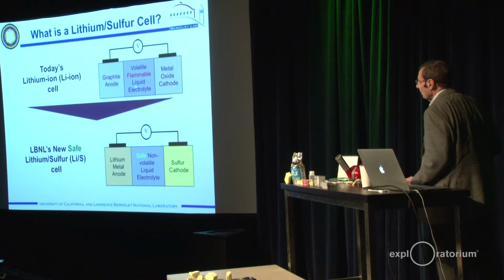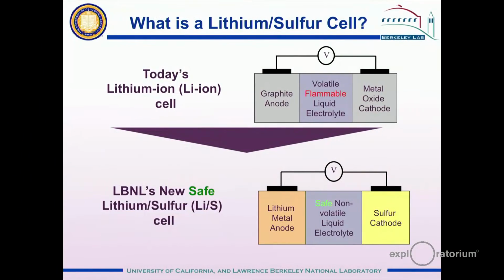We replace the flammable organic solvent-based electrolyte with a safe, non-volatile liquid electrolyte based on ionic liquids, which are non-volatile and non-flammable. And for the positive electrode, we have sulfur as the active ingredient instead of a transition metal oxide. So the lithium is much lighter weight than the graphite, and the sulfur electrode is much lighter weight than the transition metal oxide electrode. So we are saving weight because our electrolyte is non-flammable.